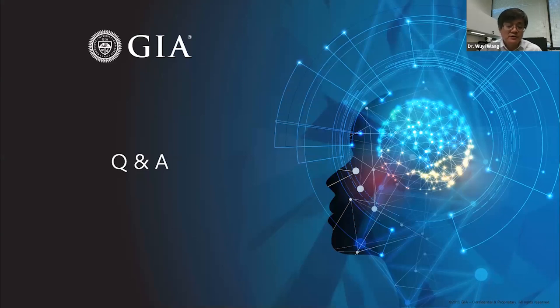Second, it could be due to fluorescence. We talk about absorption. Absorption is the most important thing that creates the color of a diamond. But for some diamonds, let's say a diamond has a reasonable amount of H3 defect and a reasonably low concentration of A center of nitrogen, the H3 could fluoresce. In addition to absorption, the H3 defect in this diamond could fluoresce green. So that will be a green color due to fluorescence. That's the second reason for green color.